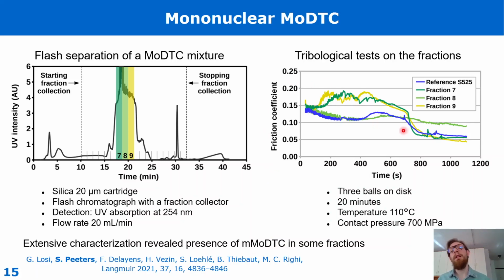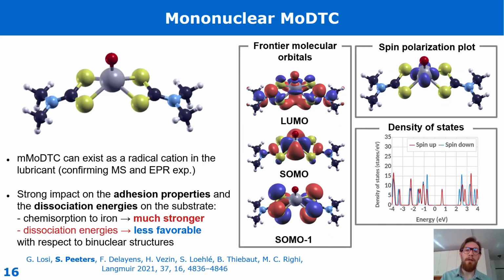So it turns out there is no fraction better than the reference, the commercial mixture, most probably because of a synergy between the compounds that are present in this fraction. So to better understand why, we carried out an extensive experimental characterization of these fractions, and it turns out that by mass spectrometry, the most important mononuclear structure is this one, with longer alkyl chain of course, and electron paramagnetic resonance revealed a particular electronic structure for this compound.